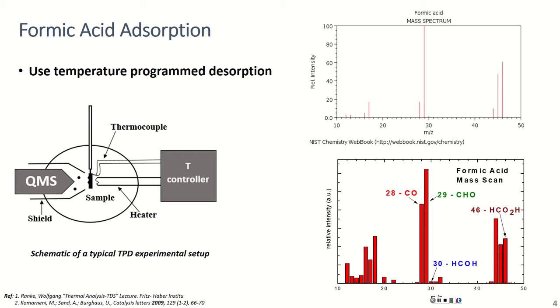Yeah, no problem. So how quickly do you ramp the temperature? It is about 1.6 Kelvin per second. That was the heating rate. We could change the heating rate, but that was the heating rate that we used.